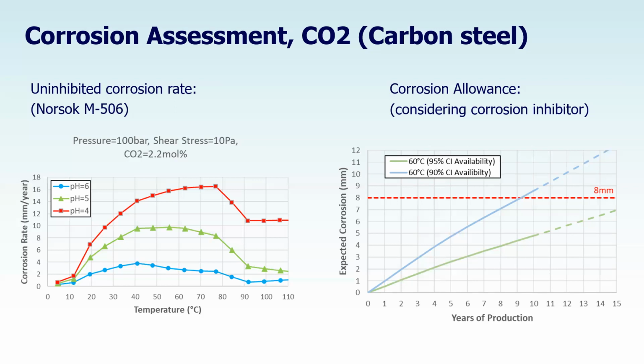So we should be really aiming for 95%. Now we know from the reports available for existing facilities that they couldn't quite meet 95%, unfortunately. So it means that specific spare and backup systems will be required to hit 95%. And the last point I would like to highlight: if we decide to prevent hydrate formation by insulating the pipeline, then higher temperatures will be maintained along the pipeline length, and actually corrosion allowance will decrease.